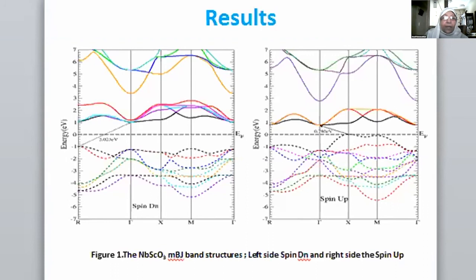So here, the spin down is on your left-hand side, and on the right-hand side you have the spin up band structure. What we can see from here is that the band gap has now opened up and become bigger in the spin down, or the minority case, and we have around 2, I'm not seeing the value, but I can just give you the value.